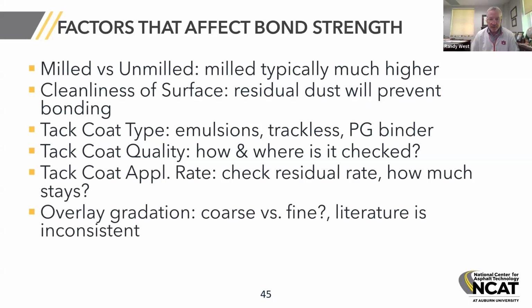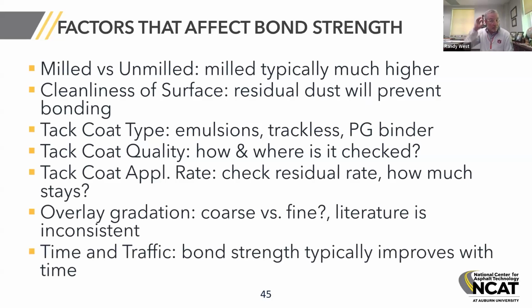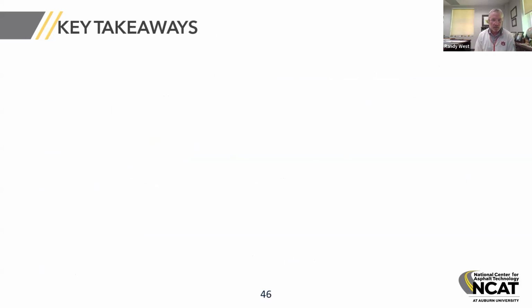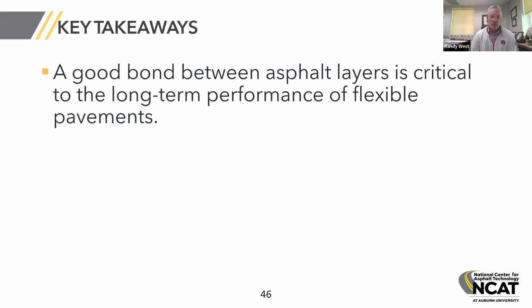Mix gradation can have an effect. The literature is inconsistent about that. We certainly saw in the NCAT study where fine mixes provided a better bond strength than coarse mixes in the laboratory. And then time and traffic. Bond strength typically improves with time, although it wasn't significant in the study that we did for New Jersey. So the key takeaways. Number one, a good bond is critical to the performance of flexible pavements.